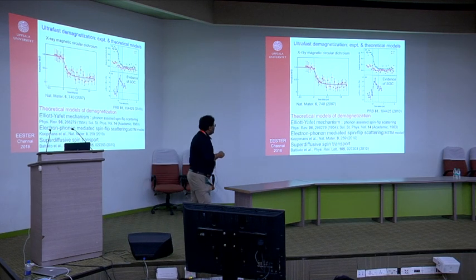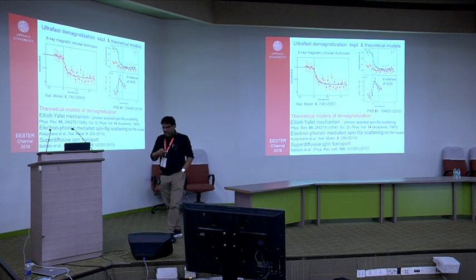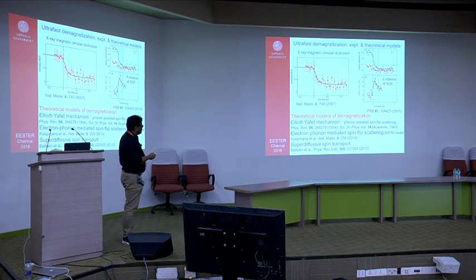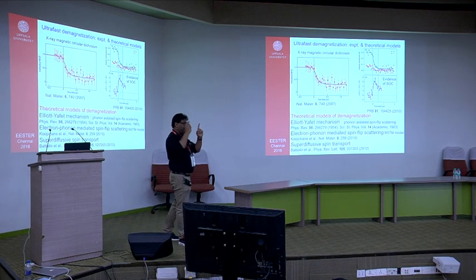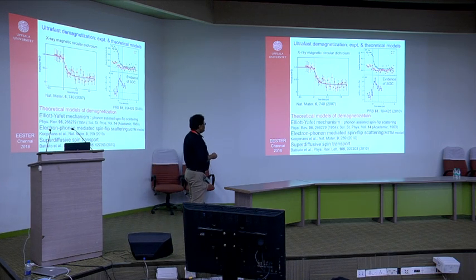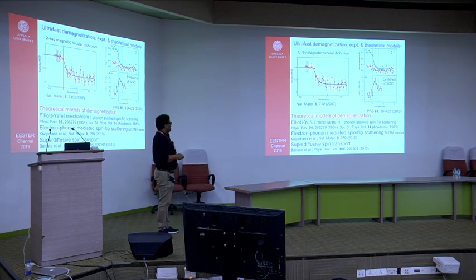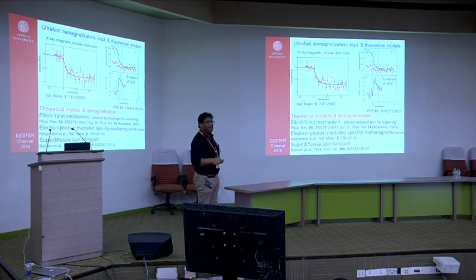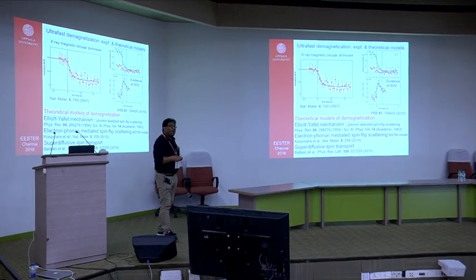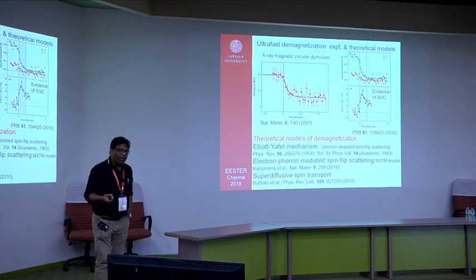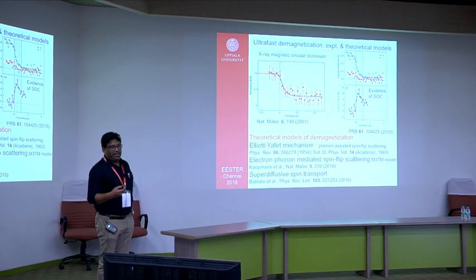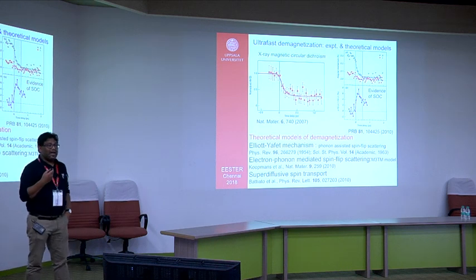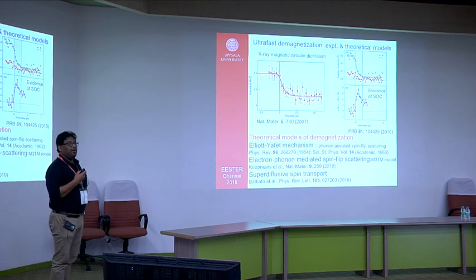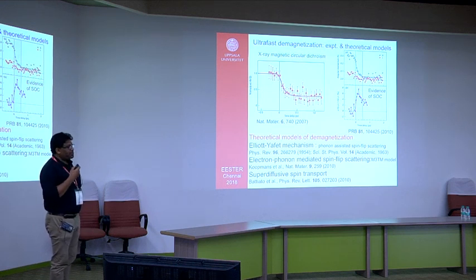Now there have been different theoretical models of demagnetization. Some of the notable models are the Elliott-Yafet mechanism, where phonon-assisted spin-flip scattering, or electron-phonon mediated spin-flip scattering, is involved. Or from our group, we have a theory called superdiffusive spin transport, which is based on Boltzmann equations. People are trying very hard to find a microscopic model, but we are still far from there. Because, as I said, there are lots of scattering mechanisms, and finding a microscopic picture of these scattering mechanisms is very difficult. We are still very far from there.